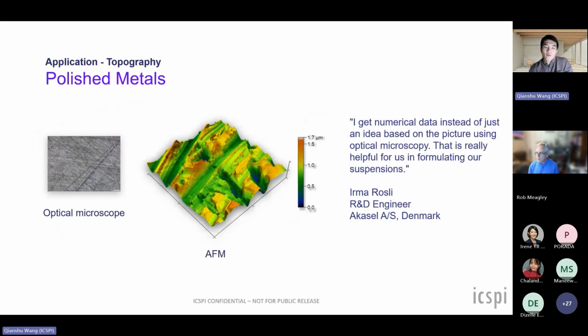Another great example is one of our customers in Denmark, Akasel, a company that produces metal polishing blends. Previously, they were using an optical microscope to assess the depth of scratches left behind after using a blend to polish metals. They want to know how deep these scratches are and what roughness is left behind, so they can use this data to further hone and develop their processes. Using our AFM, they get actual information about how deep these scratches go, numerical data instead of just an idea based on the picture they were previously getting out of optical microscopy.